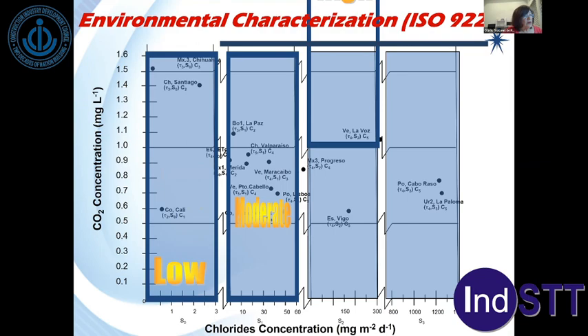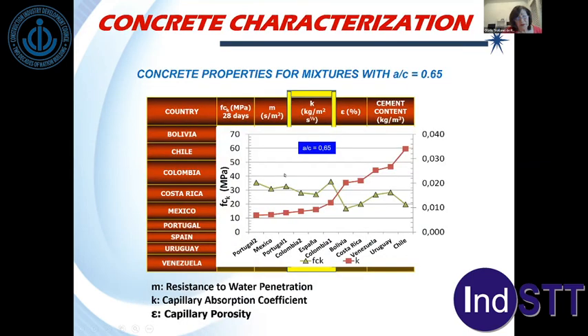is that even if you have the same materials to prepare the concrete, for example, Portugal has two mixtures made with the same material, but different compressive resistance, different quality. You can find a good relationship between the compressive resistance and the water absorption, but not for all the countries. This same behavior is observed for water-cement ratio 0.45.